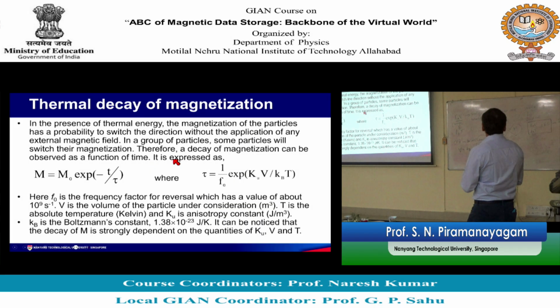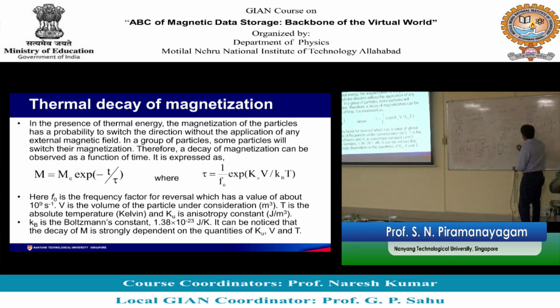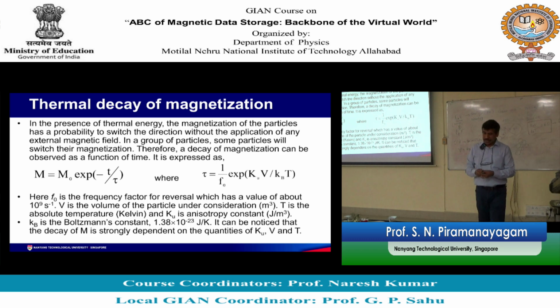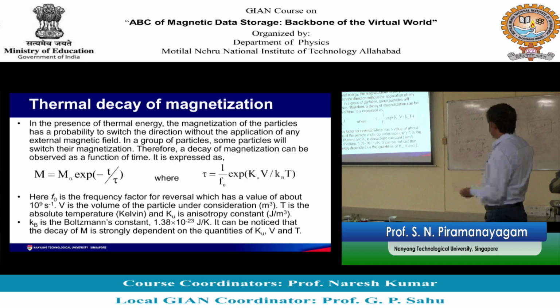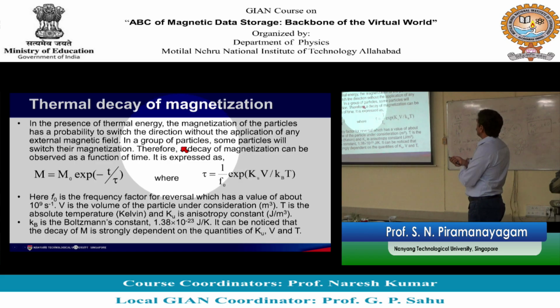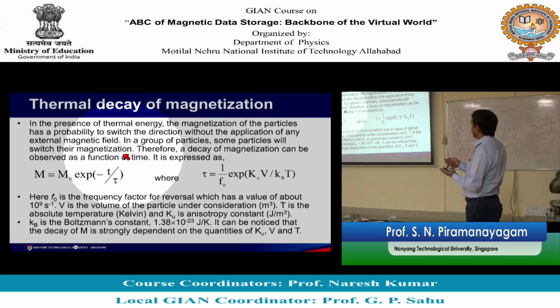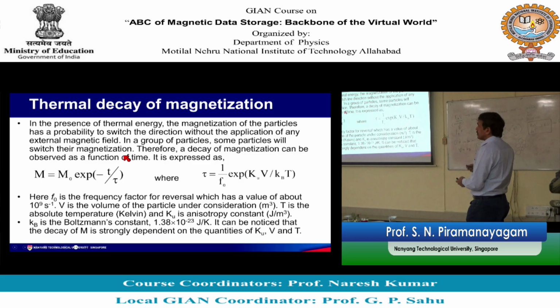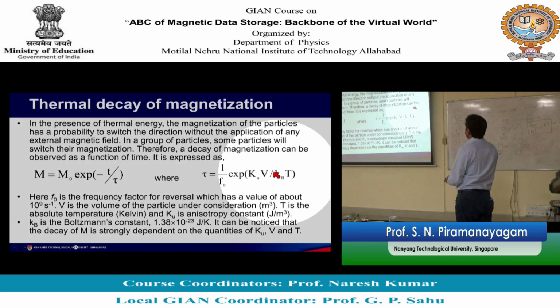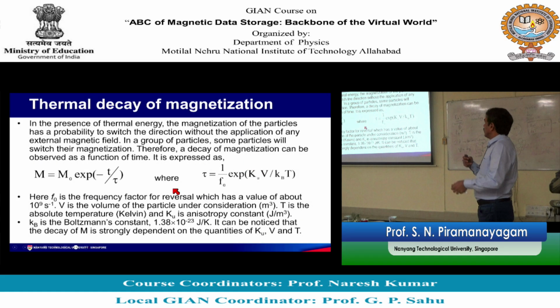Okay, so that is one thing. Secondly, in your recording media, not all grains have the same diameter, right? So, there may be some small grains, some bigger grains. See, these grains are smaller. So, they will have much lower KUV by KBT because their diameter is small and they will decay first. So, in a group of particles, some particles will switch their magnetization because they are smaller in size, their KUV is much smaller compared to KBT.